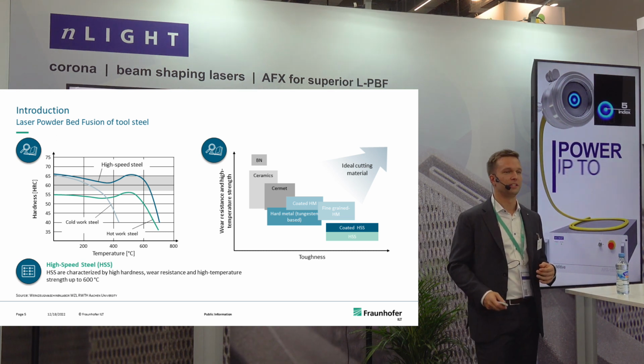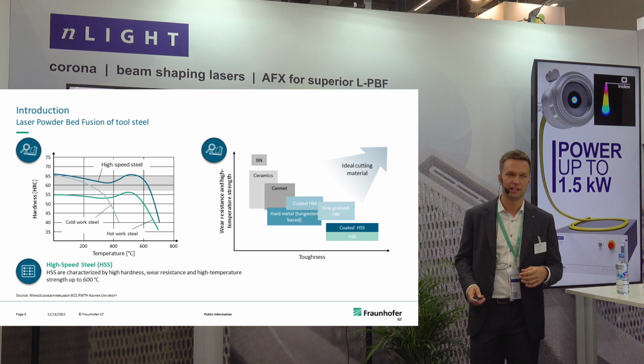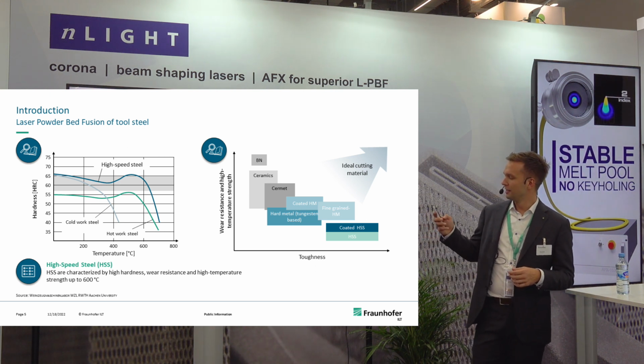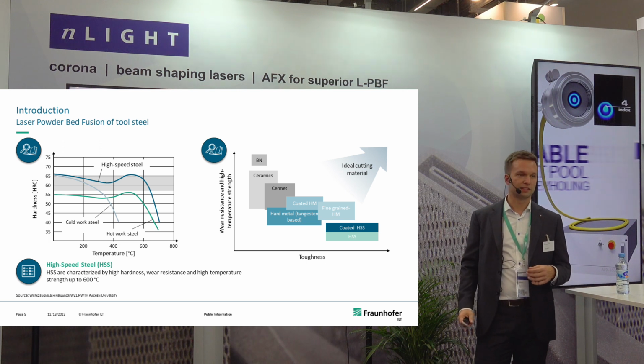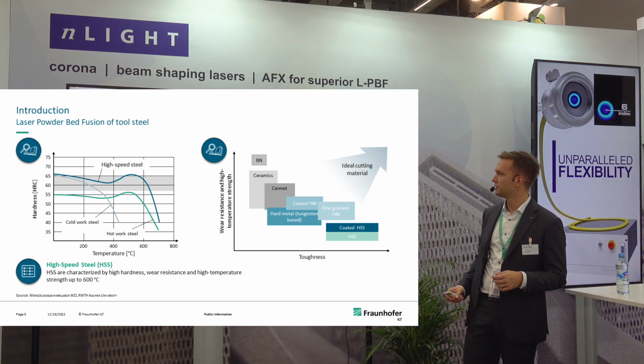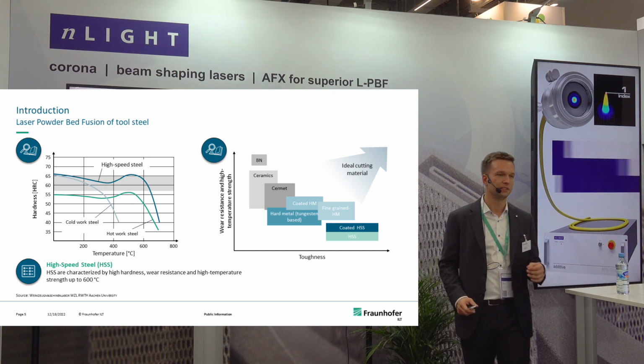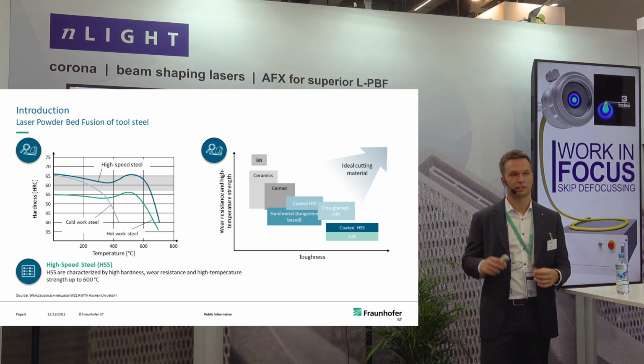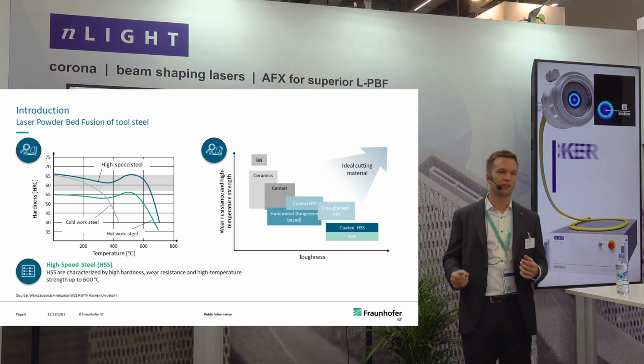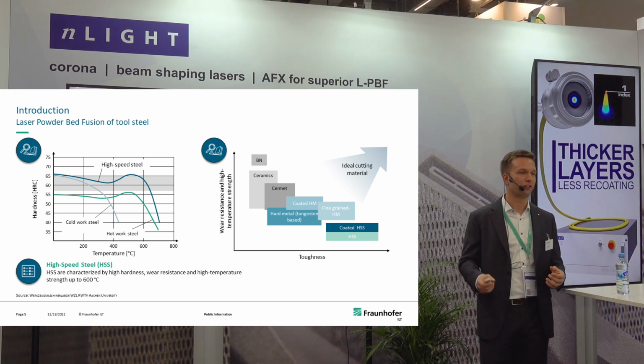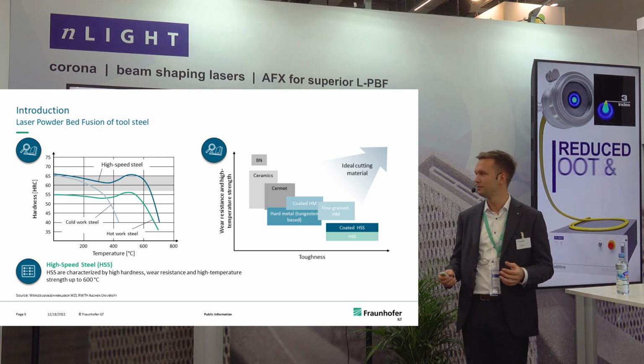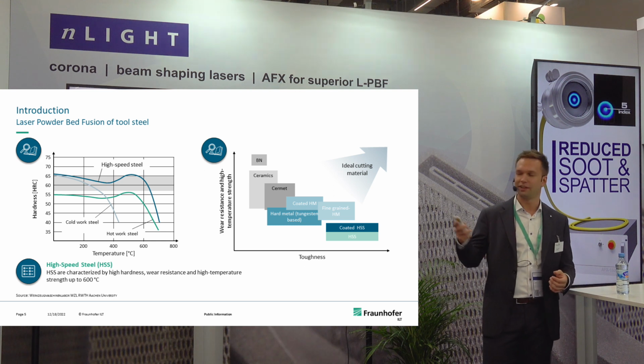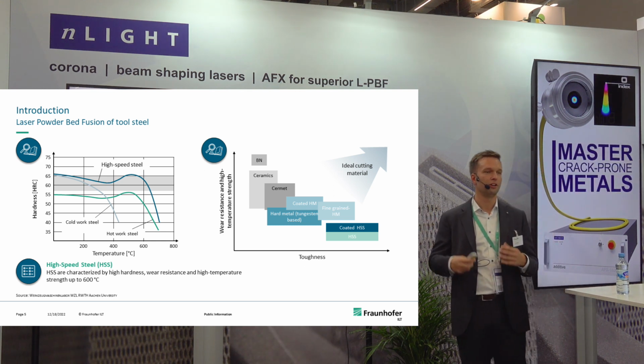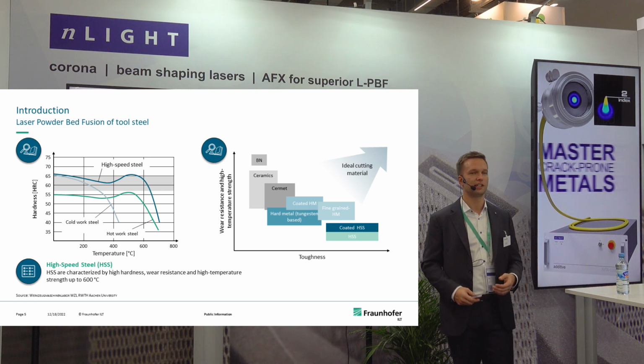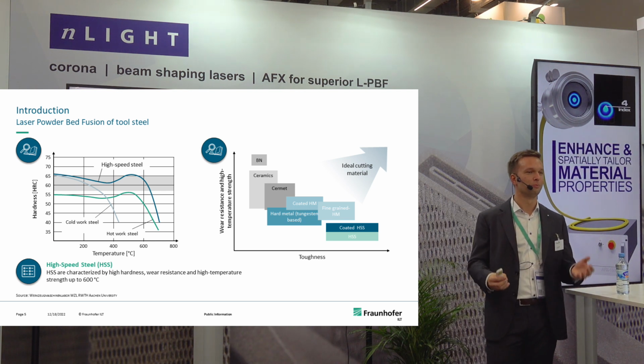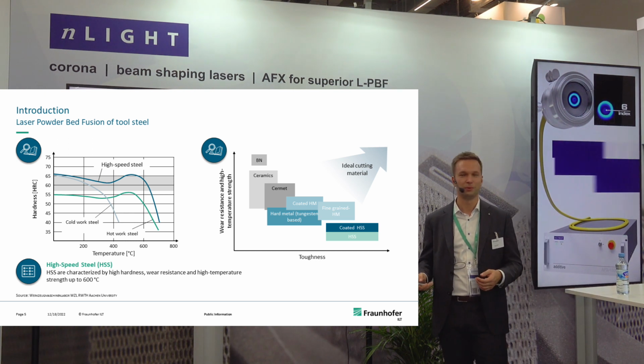And then when you look into the materials that are commonly used for cutting applications especially, you see that especially ceramic materials such as boron nitride or tungsten carbide-based cutting materials are state-of-the-art for a lot of cutting applications, just because they are very hard and therefore can be used to cut a variety of materials or to mill a variety of materials. But one of the key disadvantages of these ceramic materials is that they are very brittle, so tool failure is usually catastrophic. So either your tool breaks or it works. There's not a lot in between.